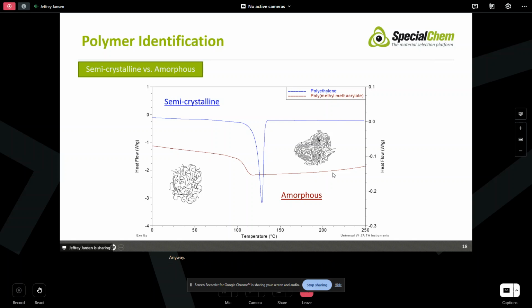Anyway, most fundamentally, what we can understand about our material is if it's semi-crystalline or amorphous. Amorphous materials have a totally jumbled structure. They have no crystalline domains, and as such, the only transition they're going to undergo is a glass transition. Semi-crystalline materials have some amorphous content, but they also have crystalline content. So as such, they're going to undergo both a glass transition and a melting endotherm. So we can understand, again, just simply by looking at the results, do we have an amorphous or do we have a semi-crystalline material?